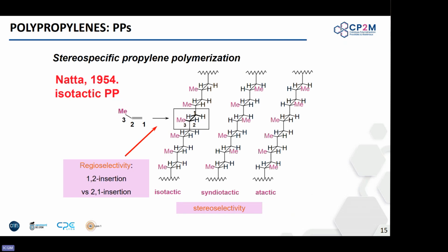I'm not going to discuss PP too much, but I want you to understand why 97% of PP produced worldwide is done by Ziegler-Natta catalysis and supported catalysis in particular. Okay, it's because it's so interesting: from a supported titanium center, you can generate geometries by tuning the way you prepare the precatalyst that will allow you to both get a regioselectivity on the insertion of propylene, okay, and also a tacticity, so a stereoselectivity. And this allows you to get either isotactic, syndiotactic, or atactic polypropylene. And the one that most of you know is isotactic PP, okay, because it's usually the one that is used, okay, and it is produced worldwide. It must account for more than 95% of the total production, okay.